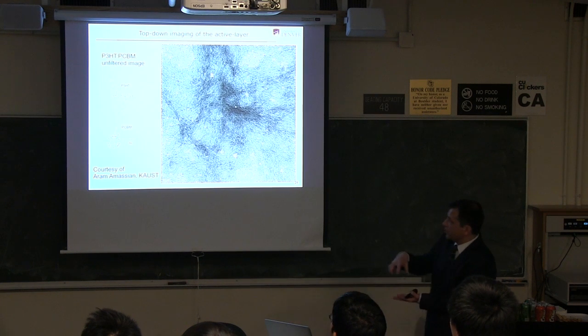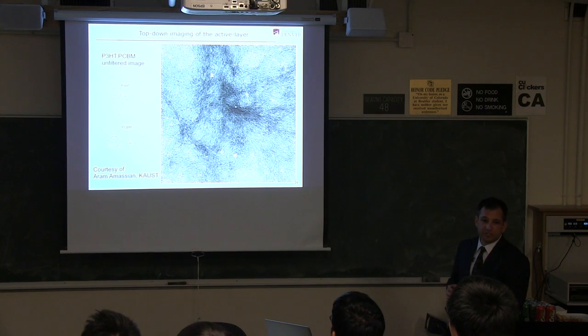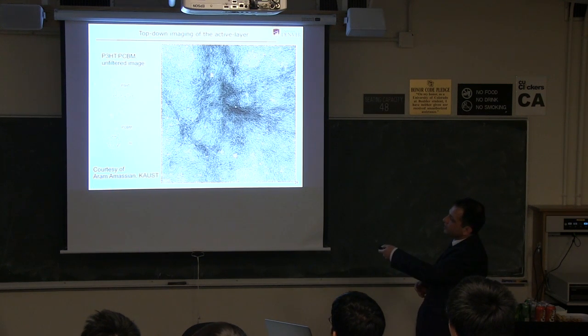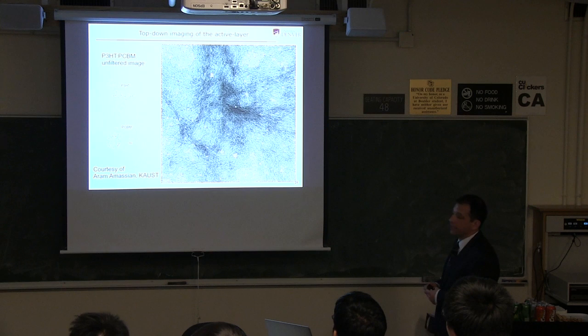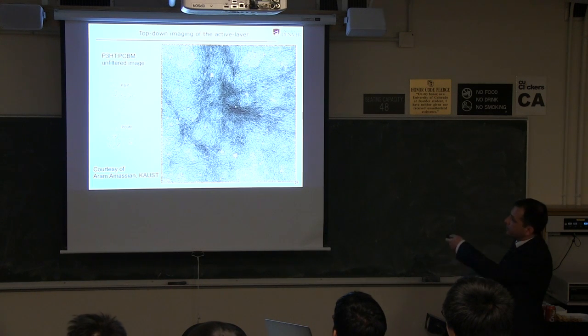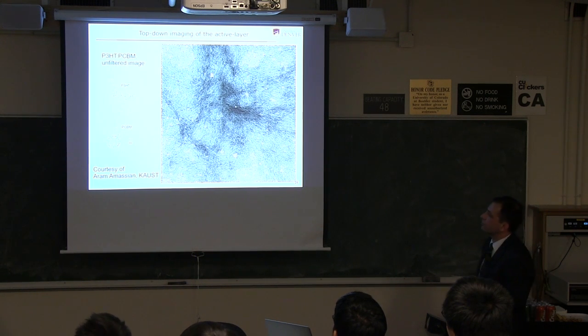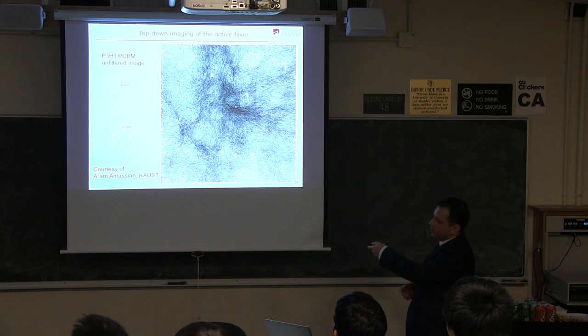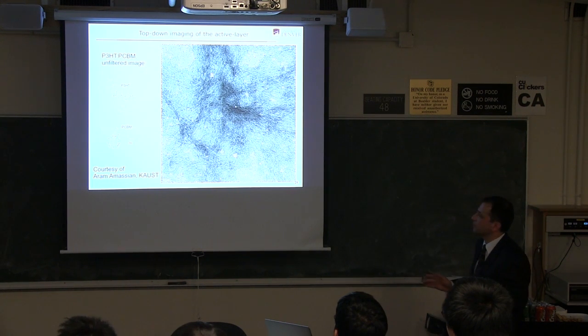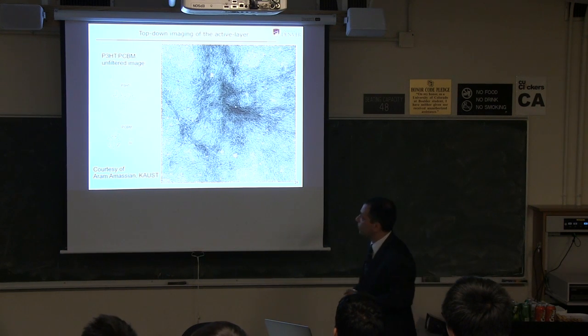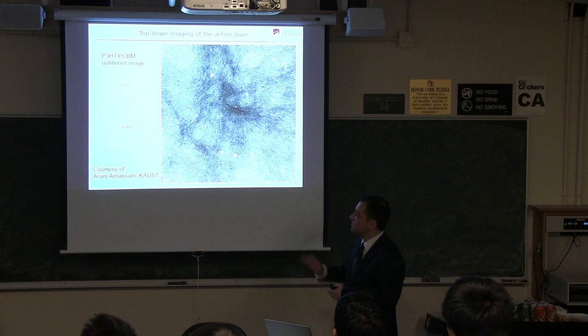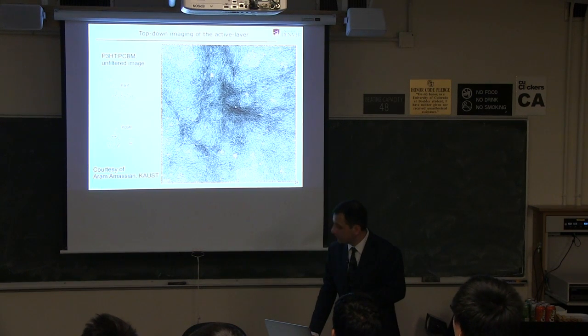If you look top down on the active layer with the TEM, you could see some of the nanostructure of the polymeric materials. And one thing you see with this material, with P3HT, is that it grows into a nanofibril structure. So you see these little thread-like features through the film. So this guy self-organizes to some extent. It's not a liquid crystalline material, but it does pack into a linear feature that's about 20 nanometers in diameter and several microns long. We think that's a good thing for charge transport, but not critical. We have lots of devices that don't show that image that work pretty well.